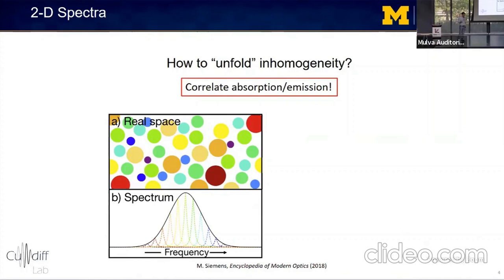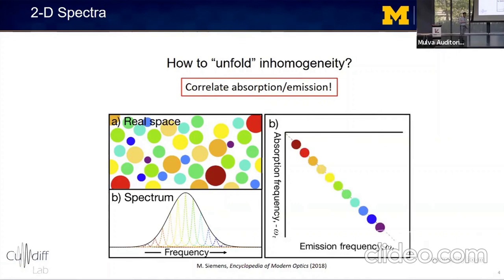And of course, as everyone in this audience knows, this is exactly what 2D spectroscopy does, where you get a 2D spectrum that looks something like this, where the y-axis is absorption frequency and the x-axis is emission frequency. And in the context of colloidal nanocrystals, each point along this diagonal line where absorption equals emission corresponds to nanocrystals of a certain size, and the line shape in the cross-diagonal direction, or the perpendicular direction, reflects its homogeneous properties.